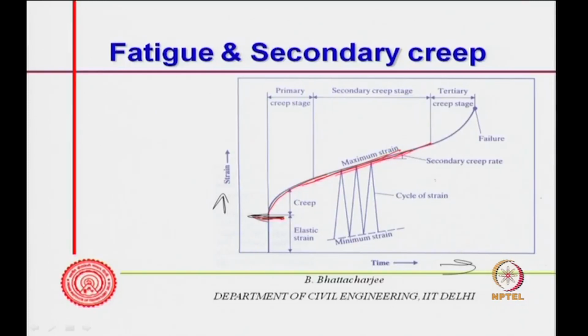As you go further, at very high strain in the long run, it may actually result in failure, because suddenly there may be a lot of deformation. So, the rate might increase again. There is a high rate here which has a tendency to reduce, and here a low rate with a tendency to increase, and somewhere here failure may occur.